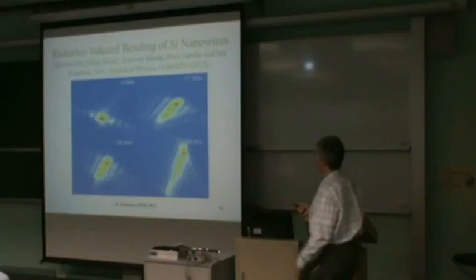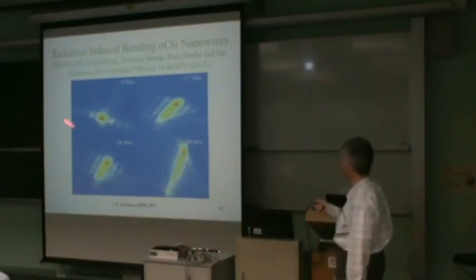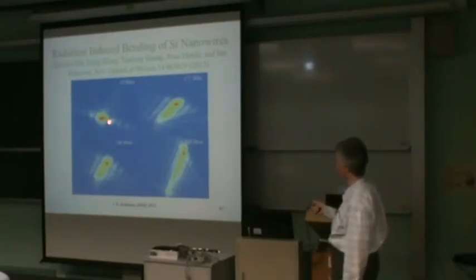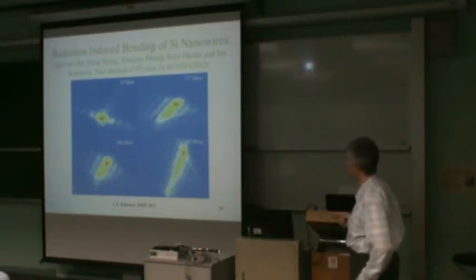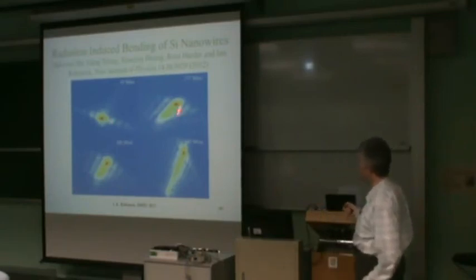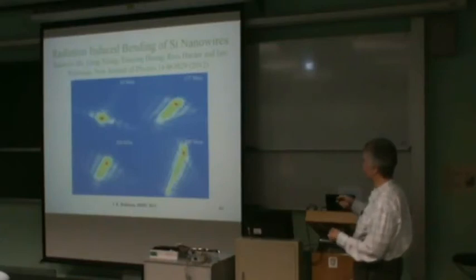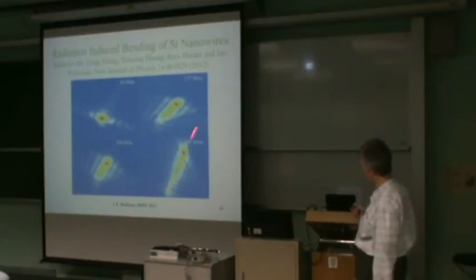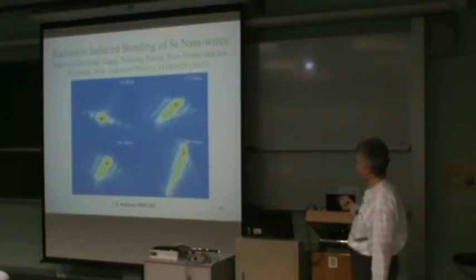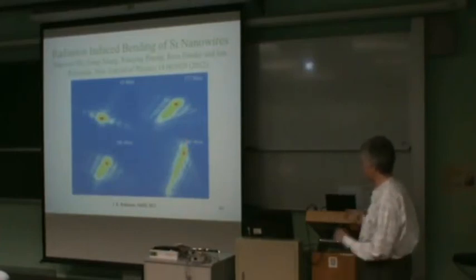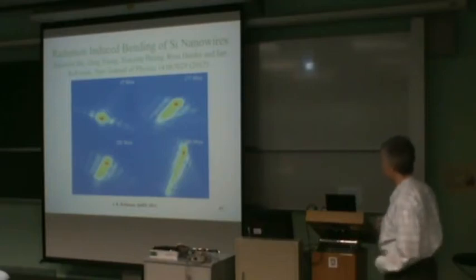So this shows early time. You get a fairly conventional square-like diffraction pattern, just looking at the center of the 3-dimensional distribution. And then sometime later, you've now got it splitting into multiple peaks, and then it becomes bigger and bigger still. So after 240 minutes, that was the last measurement we got for this particular wire before the peak disappeared.